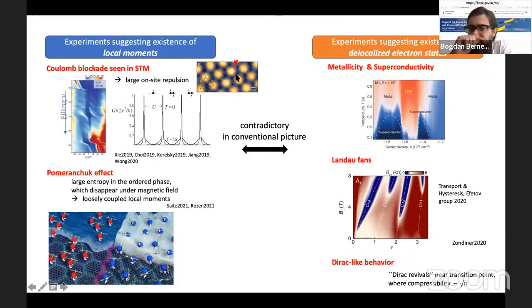So at this region, you see the triangular lattice, basically, not the hexagonal lattice. You see high concentration of charges. And moreover, if you tunnel there, you basically see a huge on-site repulsion. So all the Hubbard physics, maybe not Hubbard physics, but certainly the interaction physics is concentrated at the AA sites. Moreover, you can see some other effects, such as Pomeranchuk effects, large entropy in the ordered phase, which disappears under magnetic fields, basically features of loosely coupled local moments. And this picture is really obviously contradictory to the picture, to the phase diagram seen in transport, where you see metallicity and superconductivity, and then you see Landau fans with different Chern numbers and other, obviously, itinerant electron behavior.